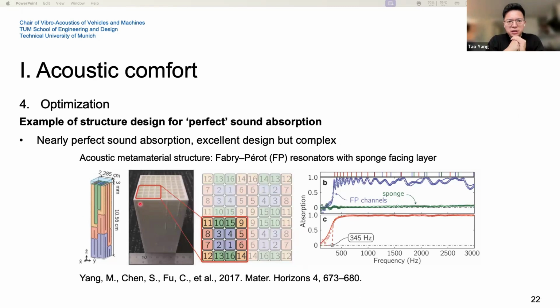Here I'd like to introduce something I'm currently working on. It's about optimization, but it's not about metamaterials or metastructures. In my work, I try to reach the optimized sound absorption, but with a thinner structure or lighter material. Why? Because although we can reach nearly perfect sound absorption after 500 hertz with a very well-designed metamaterial, in this metamaterial they use 4 units to combine one sound absorber, and in each unit there are 16 different parallel resonators. In the end, they added one 3 mm layer of sponge to generate such great sound absorption.